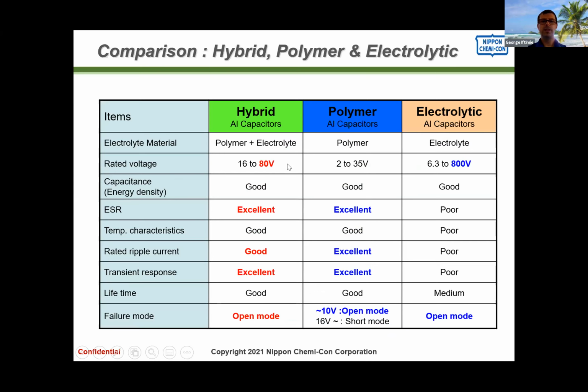A little bit on the voltage. Hybrids are usually available up to 80 volts. Some competitors have higher voltage than that. But we found that we're working on a 100 volt rated voltage polymer, but humidity resistance is much lower for above 80 volts than it is for 80 volts and below. And then there's some points of ESR and so on.